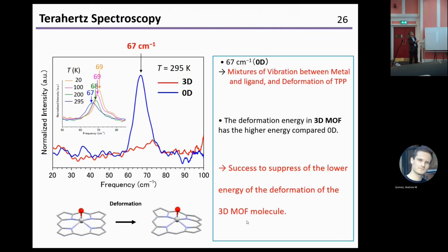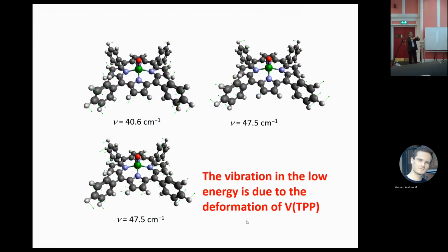Then we measure the terahertz. For the zero-dimensional material, we observe a sharp peak at the 67 wavenumber. This is the deformation of the molecule and also the stretch mode of the metal ligand. However, in the three-dimensional MOF, there is no peak because it is rigid. Deformation is suppressed. Stretch mode is suppressed. So we succeeded in suppressing the low-energy deformation in the three-dimensional MOF. In the theoretical calculation, some deformation of the zero-dimensional molecule appears around here. This is observed in the terahertz region.